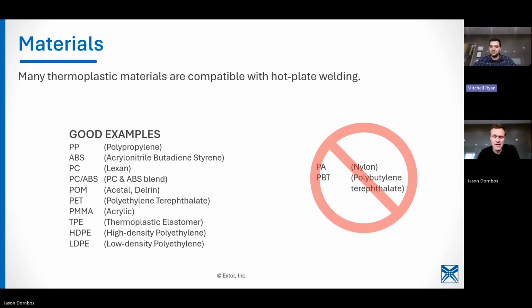Specifically on degas bottles and probably in other applications, the weld is very thick. Because of the way plastic shrinks after it's molded, there is sink in that weld surface, and on a big part with lots of internal ribs, there's sometimes pretty large amounts of sink, to the point where we have to melt a lot of depth, like 0.1 inches into that plastic, which doesn't sound like a lot, but it is a lot, especially on a large surface area. You get a lot of force, and you're pushing to get full weld penetration.